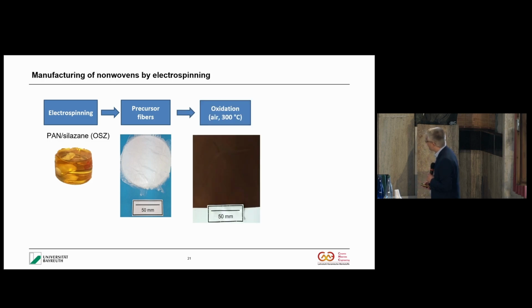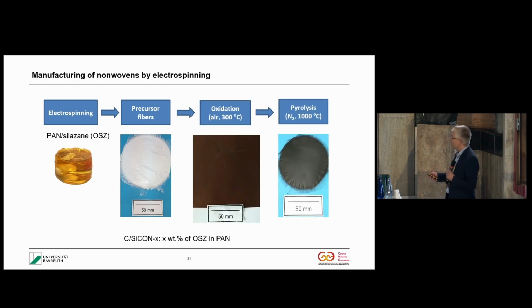So here you can see the processing steps. First of all, you have the electrospinning of the copolymer. You have the non-woven mat, which is still in the polymer state. Then you have the oxidation, so that means a cross-linking step, and then the pyrolysis at about 1000 degrees Celsius in nitrogen, leading to these non-wovens.